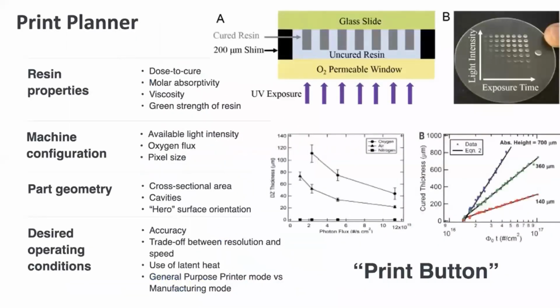And so we've measured this out in quite great detail under a lot of different conditions, a lot of different resins, and the dead zone thickness as a function of light intensity. When there's no oxygen, there's no dead zone. If you have air coming through the window at low light intensities, the dead zone could be 80 microns, stripped down to 20 microns. Replace air with pure oxygen, you grow the dead zone.